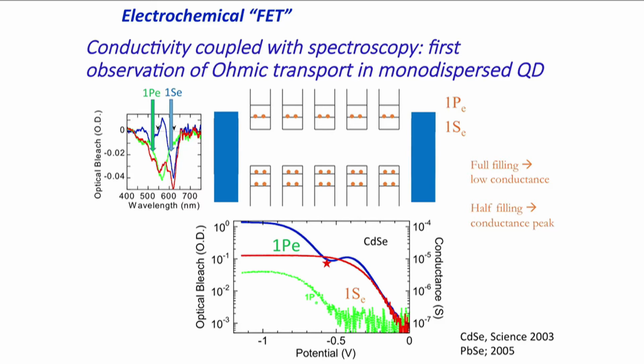But then, of course, the next state is not infinitely high. And so if you raise the bias a little bit further, then you'll see additional conductivity coming from those states. And the fact that the conductivity is higher here is in part because these are electrons that have high energy. They can hop more easily, and there's also a higher degeneracy of state at those levels.